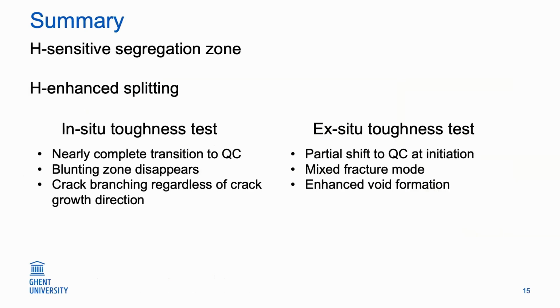With that, I will give a very short summary. So we clearly identified a very hydrogen sensitive segregation zone in this type of material, with the bainitic bands, with the manganese sulfide, with the martensite-austenite components. We saw hydrogen enhanced splitting for both orientations, but mostly for the LS, this had a big influence because these are crack arresting splits. And then for the big differences between in situ and ex situ, we see that in situ, there's almost no blunting, there's complete quasi-cleavage of the crack growth region, and there is crack branching regardless of the specimen orientation.